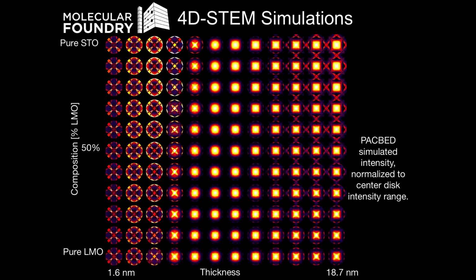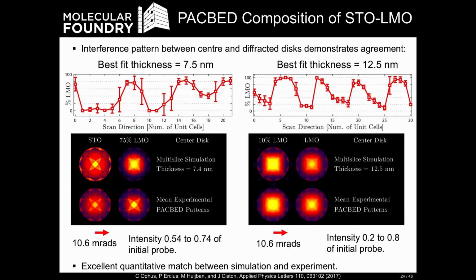If I flip back, if you look at the pure STO to pure LMO, even for the thickest sample, the patterns are still quite similar to each other. It's the details of the patterns, exactly how bright the different disk overlap regions are, that provides us with our compositional signal vector here. This is the final overall plot showing how good the agreement is between the experiment and the simulation. The simulation and experimental images are much more similar to each other than the experiment at two different compositions or the simulation at two different compositions.